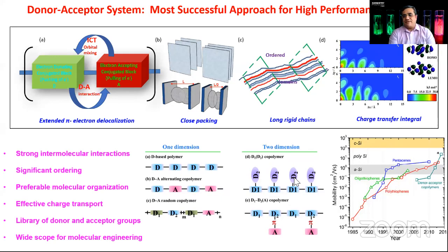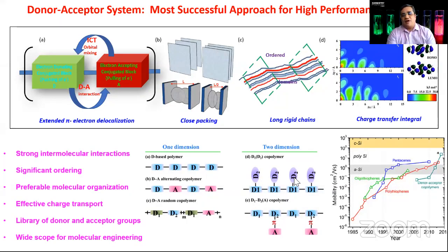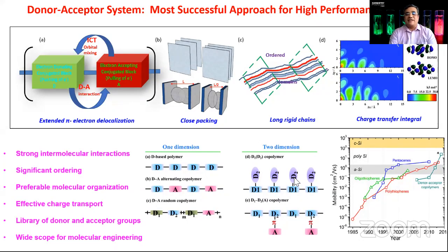Using the donor-acceptor approach, we can have a donor-based polymer for hole transport only, or a donor-acceptor low band gap ambipolar type, or a completely acceptor backbone for N-type. Looking at the chart, among the various types of materials evolved since 1985 to now, you can see the donor-acceptor approach has really taken a quantum jump. We are now almost close to the polycrystalline silicon regime, achieving mobility at ten or higher.